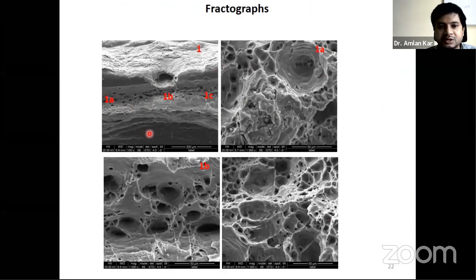And this is the fractograph. It shows that the fracture surface is composed of some particles, as well as regions where the fracture surface does not have particles. So it is a transition zone that actually leads to the fracture: the thermomechanically affected zone and the base metal or weld nugget, that interface, is actually leading to the fracture.